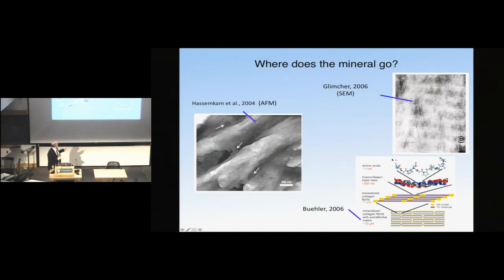This is a TEM image where the dark phase is mineral. Where a lot of electrons go through are regions that are very poor in mineral. And it's clear that there's a banding structure which is associated with the nanostructure of collagen that I'll get into in a moment. But then there's this AFM image which shows a fibril that has just an enormous amount of mineral on its exterior, and so the plot thickens.